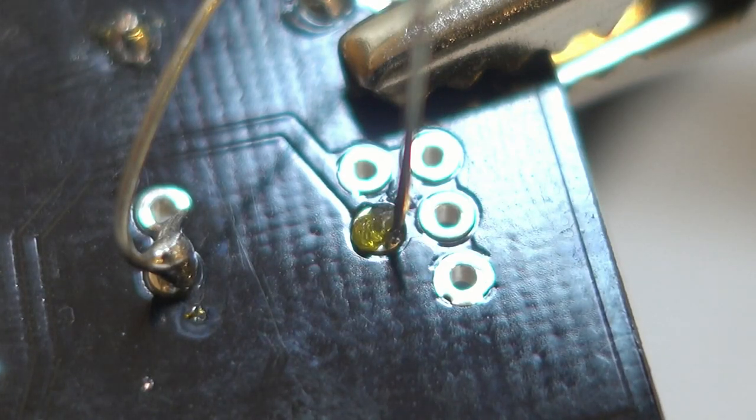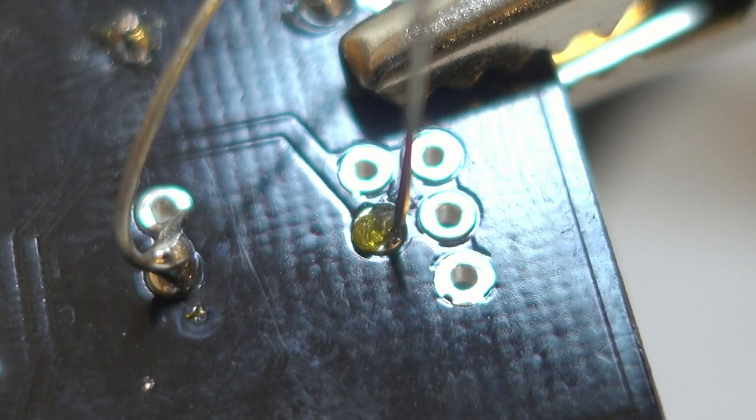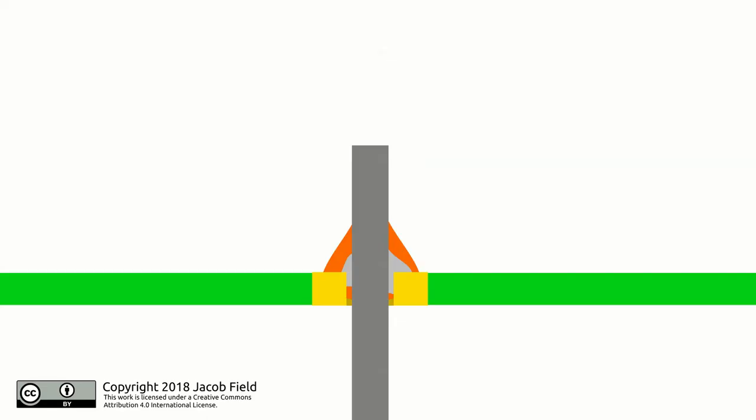This is a flux joint. Similar to a partial joint, solder has only bonded in a few places, and flux from the rosin core has filled the cavities. While it may feel and look secure, the solder may not even be making electrical connection. In this cross section, you can see that most of the space is occupied by flux, shown in orange. This can be fixed by applying heat and more solder, but in some cases you may need to clean out the excess flux first.